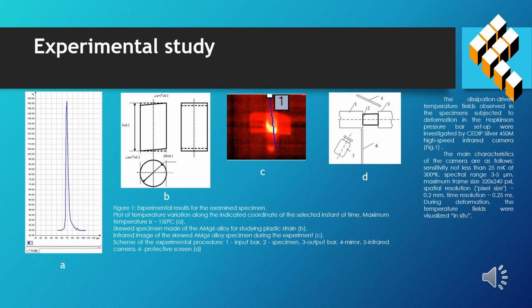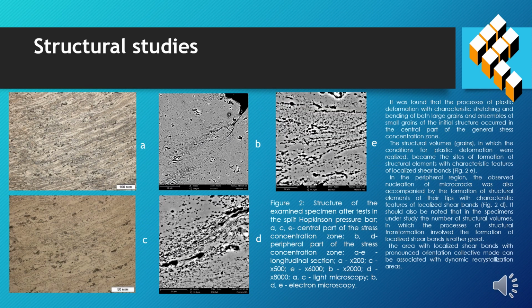under these loading conditions. The results of structural analysis of the specimens after testing on the split Hopkinson pressure bar are shown in Figure 2. The structural volumes, grains, in which the conditions for plastic deformation were realized, became the sites of formation of structural elements with characteristic features of localized shear bands.